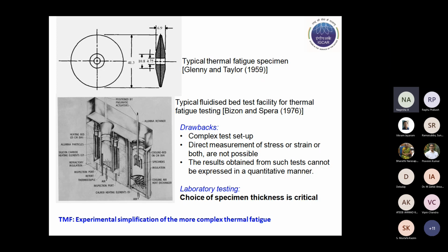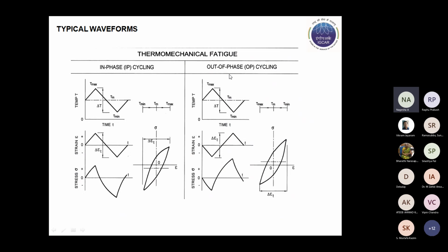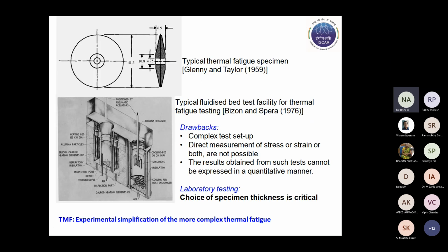The earliest studies related to thermal fatigue are credited mainly to Glenny and Taylor, where Glenny devised a specific testing technique. It is actually a testing of a turbine blade for thermal fatigue, and this kind of thing is called Glenny's discs. There is a fluidized bed testing facility which was employed for this kind of test, wherein the sample is changed, or shifted repeatedly, from a high temperature region to a low temperature region.